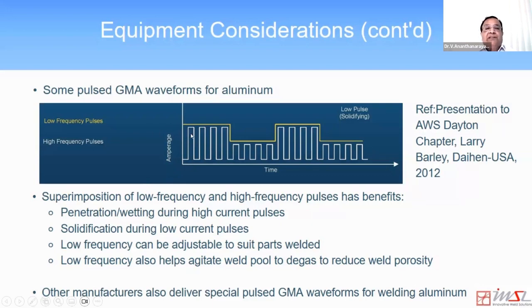You can see here that these are not low frequency and high frequency, but low amplitude and high amplitude. I have an error here in the slide that I will correct before sharing it. High current amplitude and low current amplitude pulses, with penetration and wetting during the high current pulses and solidification during low current pulses. Why do we need this?